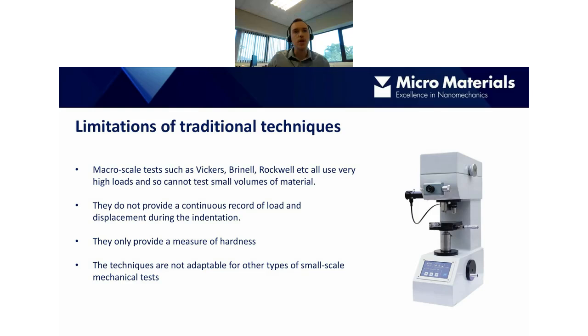They also do not provide a continuous record of load and depth during the indentation. They're essentially designed to make a big indentation into the material, and therefore we don't get this record of depth as the indent progresses. Of course, they only provide a measure of hardness, so we can't really get any other information such as modulus or any time-dependent behavior.